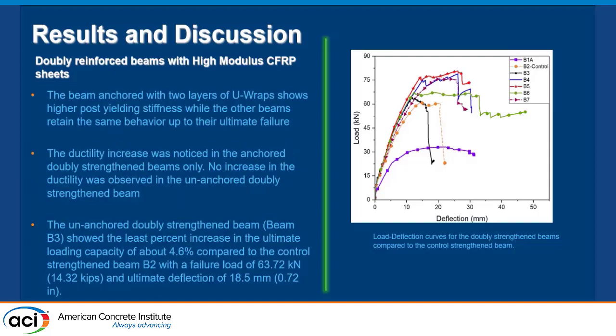So the beam anchored with 2 layers of U-wrap shows higher post-yielding stiffness, while the other beams retain the same behavior up to the ultimate failure. So the ductility increase was noticed in the anchored double strengthened beams only, and we didn't see any increase in the ductility in the unanchored doubly strengthened beams. Even though we are using the compression layer, without anchorage we didn't see noticeable ductile behavior. So the unanchored doubly strengthened beams showed the least percent increase in the ultimate loading capacity, about 4.6%, compared to the control 1, B2, with a failure load of 14.3 kips and deflection of 0.72.